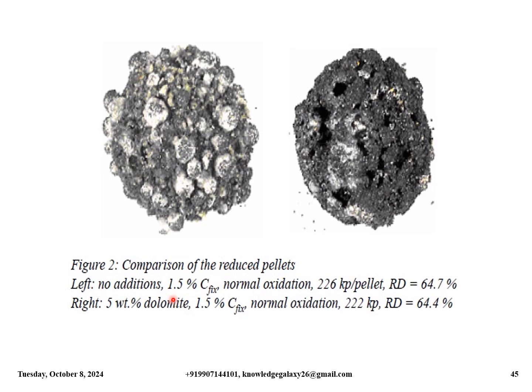So this is figure 2, which shows a comparison of the reduced pellets. This left side has no additions and 1.5% C-fix, normal oxidation, 226 kp per pellet, and RD was 64.7%. And this right side part is 5% weight dolomite, 1.5% C-fix, normal oxidation, and 222 kp, and reduction degree was 64.4%.